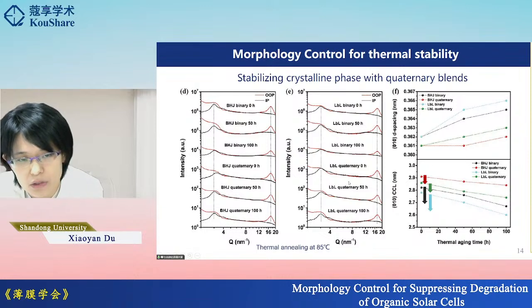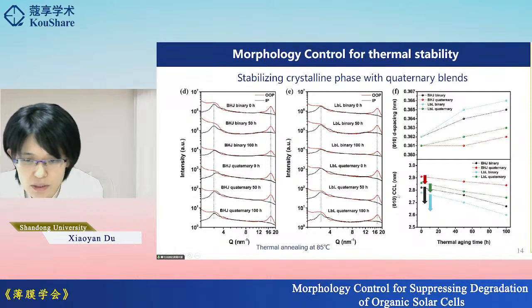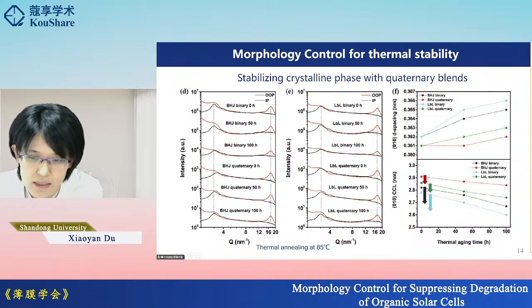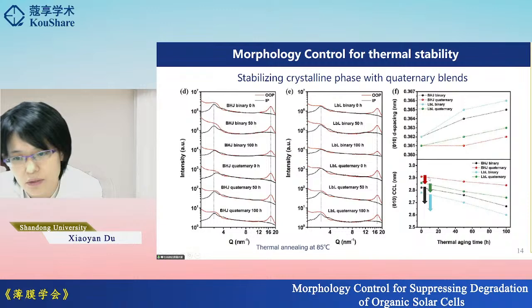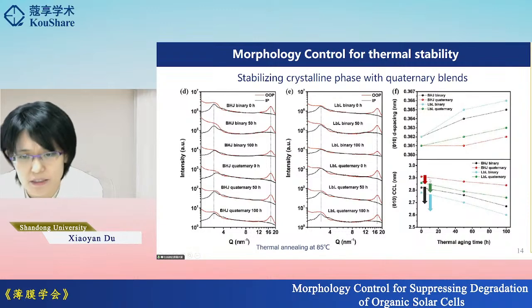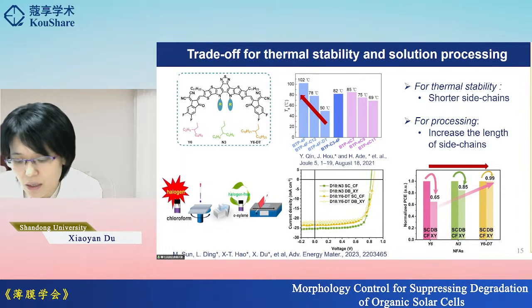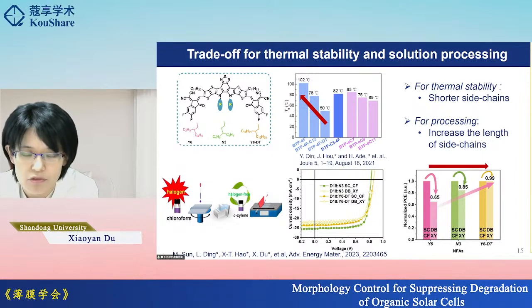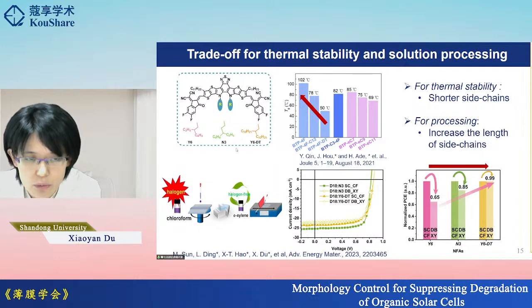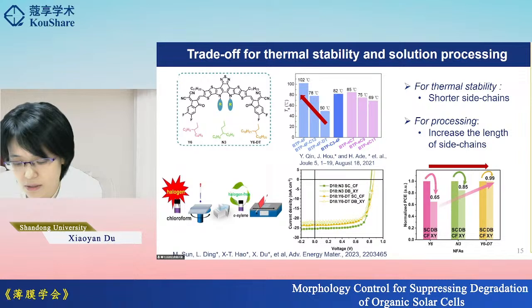The reason can be seen from the GIWAXS. Here, this is for the binary under thermal annealing for different times, and here are the quaternary blends under annealing for different times. From the quantified crystal coherence length, we can see that the quaternary can obviously suppress the changes in the crystallinity in these blends. So we can use multinary blends to enhance the thermal stability, but from molecular level engineering, how to increase the Tg or the thermal stability of the small molecule acceptors?